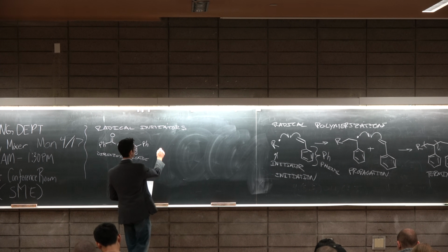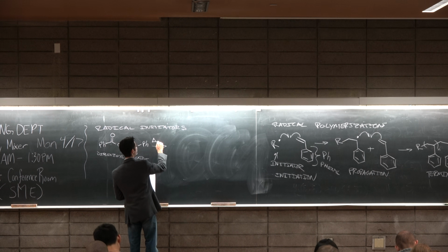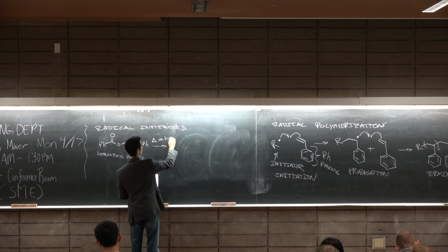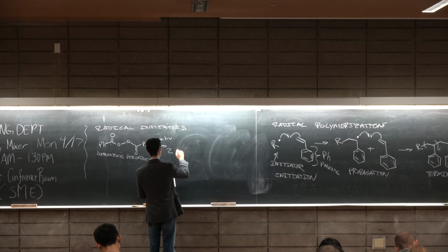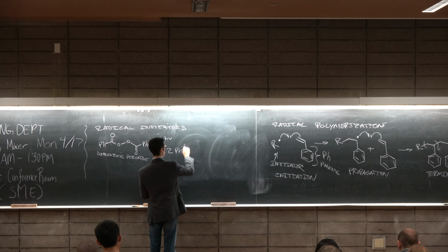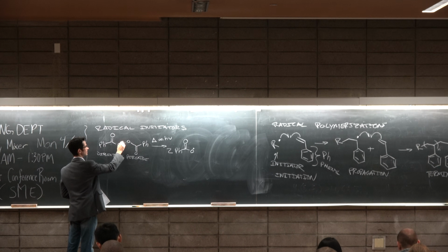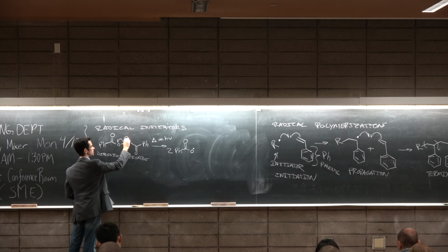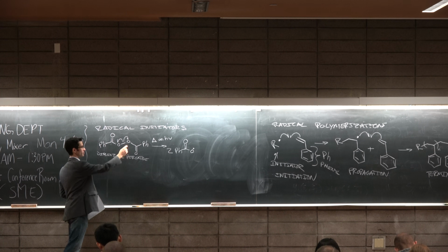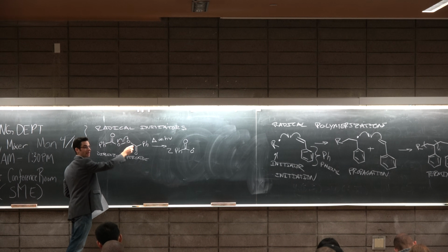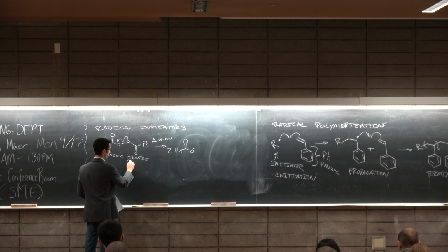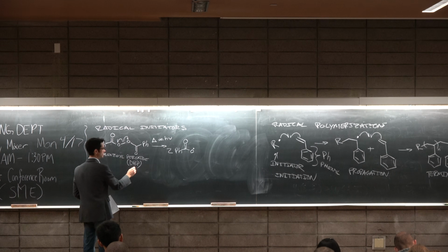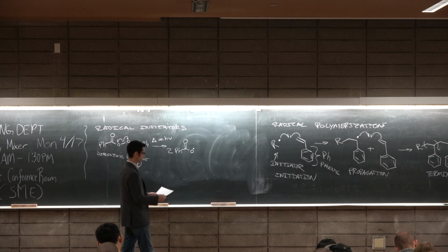And it dissociates under either heat or light to give you two benzoyl radicals, where this bond is susceptible to dissociation, and the two electrons represented by this bond go to either side of the dibenzoyl peroxide, which is abbreviated DBP sometimes in the literature.